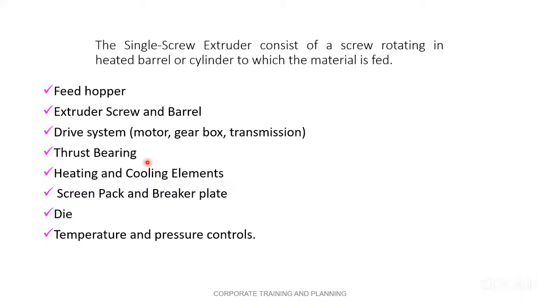Hence, this thrust bearing helps the rotation of the screw. I told you there are two types of load. One is axial load. Axial load comes from the weight; the screw is maybe 22:1 L by D ratio, and therefore it is long. It should withstand that at the time of rotation. And there is a tolerance of only a few millimeters between the barrel and the flight of the screw. The screw should not touch the inside of the barrel.